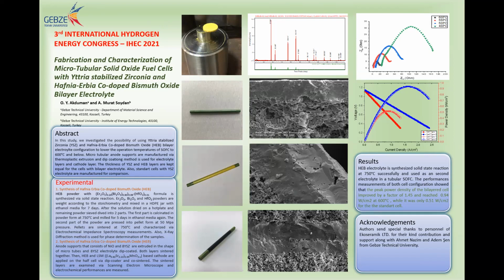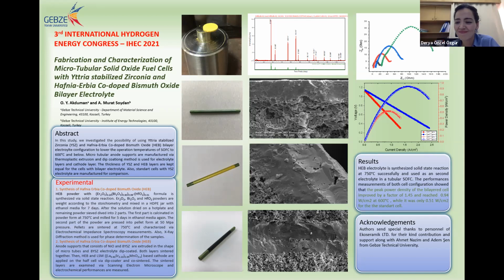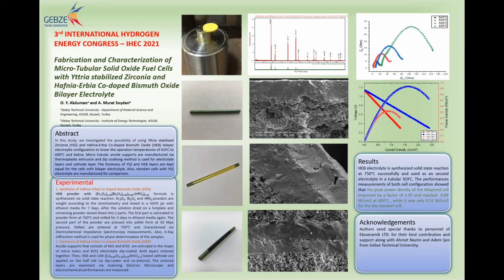These materials have super high ionic conductivity, and when in contact with the cathode material and the gas phase there, the exchange reactions are accelerated a lot. Basically, oxygen intake is higher than the other components. So you can pump more oxygen through the electrolyte if you use a bismuth-based electrolyte. Oh, okay. So the net current the cell produces gets higher, and you get better performance.